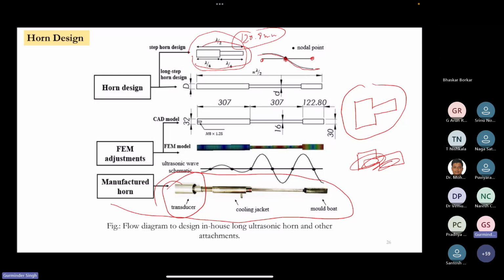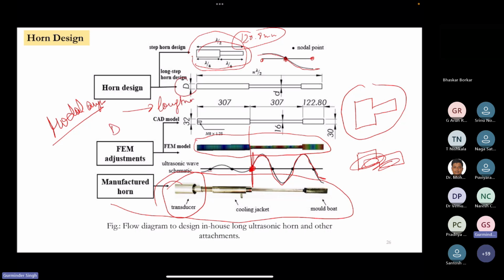But for this one there are around six nodal points, and it is getting amplified at the step, at the third nodal point, and you are getting the same amplification at the right end of the horn. So you have to do a lot of FEM around this. You have to do modal analysis, which gives you the vibration frequency in the longitudinal direction. It is really important because you have to take care of the left-hand side diameter D and the small diameter d, and also the length.